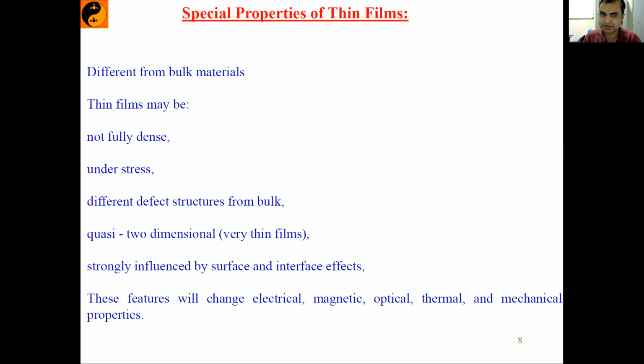They are under stress. Remember, when I say that they are under stress, stress means there is a change in its unit cell lattice parameters. And that change in unit cell lattice parameter can arise because you are integrating that thin film on a given substrate, on a given platform, and that substrate will have its own unit cell. So that own unit cell will not allow that incoming thin film to adopt its original unit cell lattice parameter. So what it does, it forces that particular evaporants, when it is rearranging itself on the substrate, to adopt the substrate's unit cell lattice parameter.